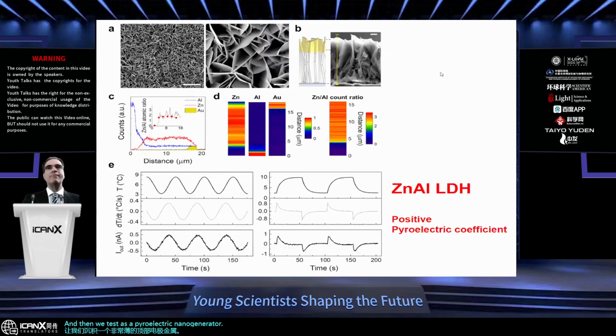Here you see an example with zinc aluminum LDH. As you see at the very bottom left, these three figures represent the test with sinusoidal temperature variations. The derivative of temperature with respect to time, of course, is also sinusoidal, but with a 90 degrees phase shift. And then you see that the current is very accurately proportional to the derivative of temperature with respect to time. That is, this output current is truly a pyroelectric current.